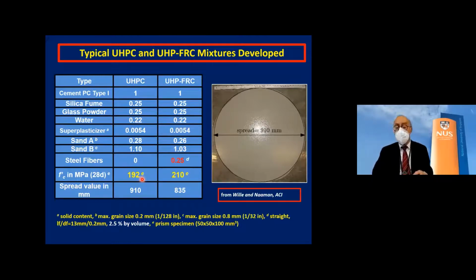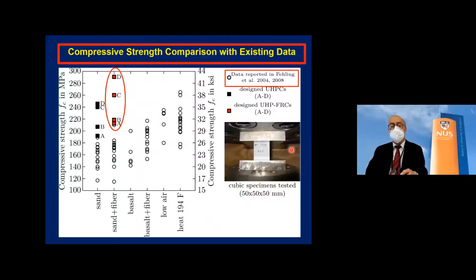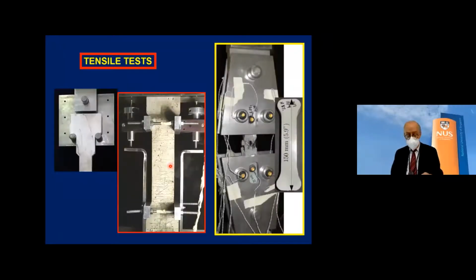192 megapascal without fiber, 210 megapascal with fibers, and a spread of the inverted cone test, which is one of the measures of the flowability of ultra high performance concrete. Our test results were in the range, in fact higher, than that published by Professor Fehling for a very large number of data. And so we were very confident that we had a good mixture.